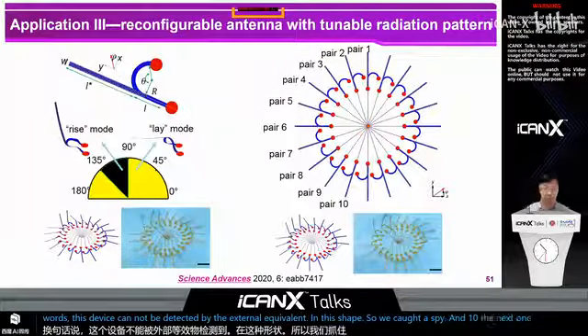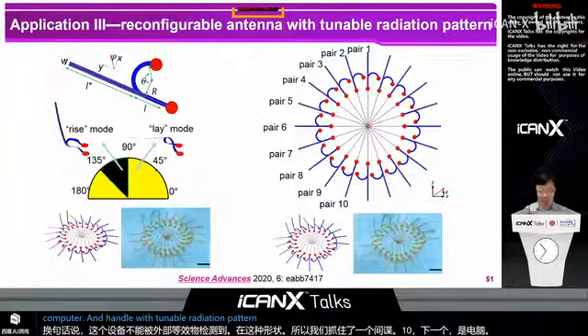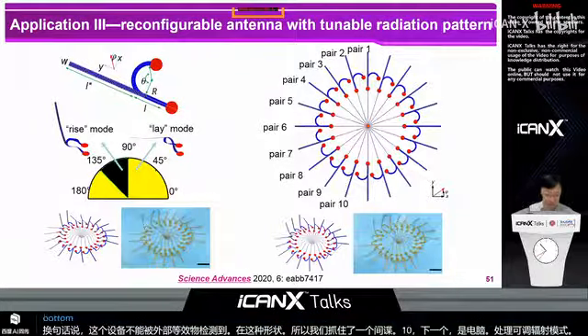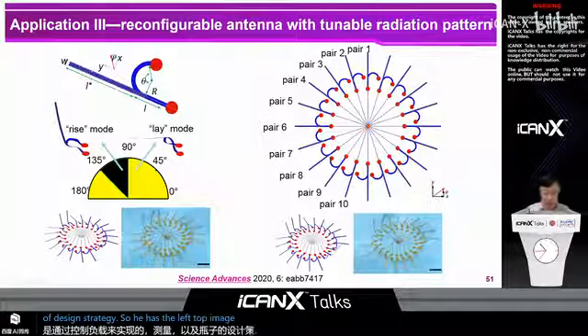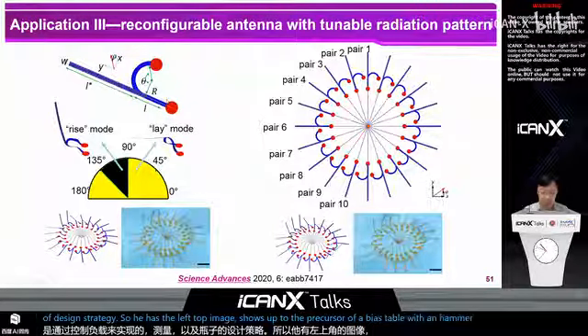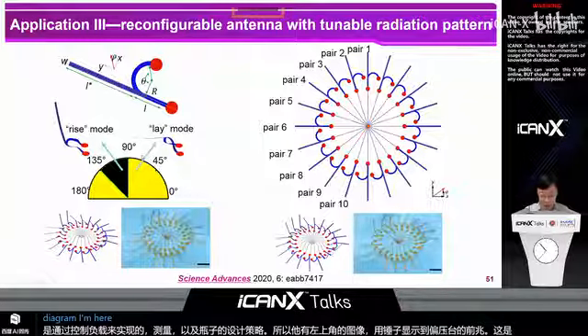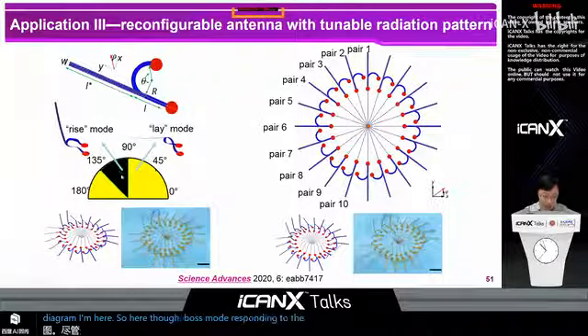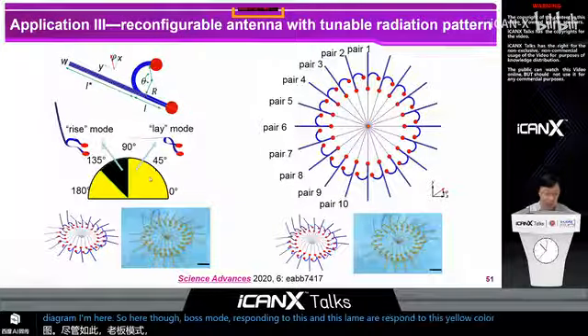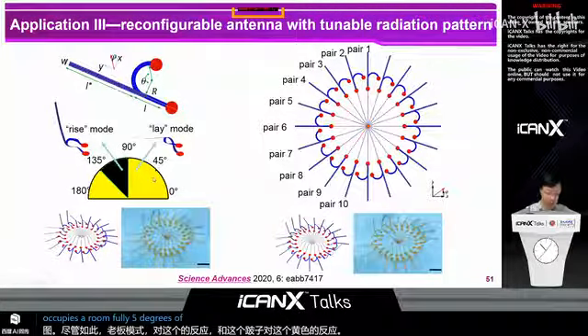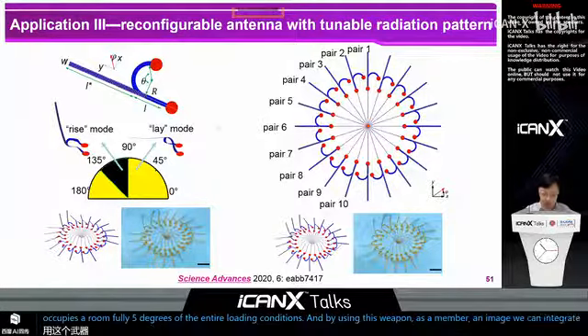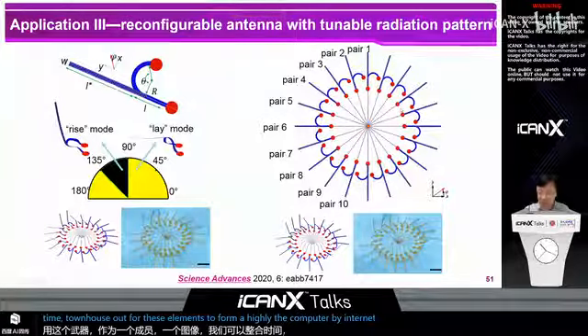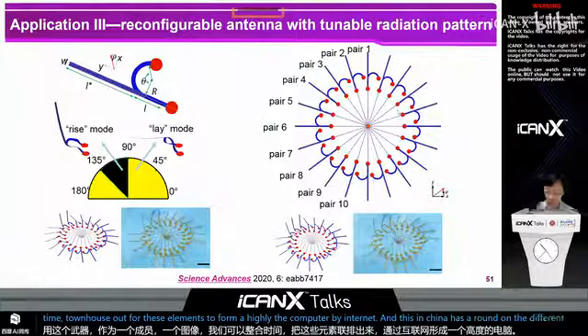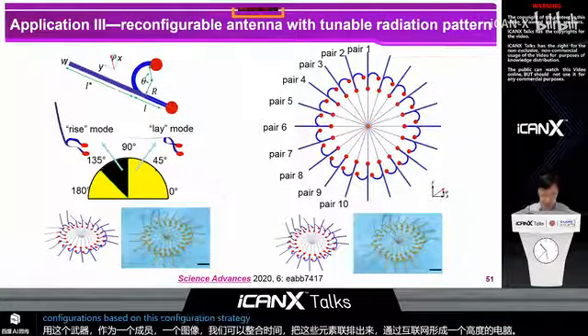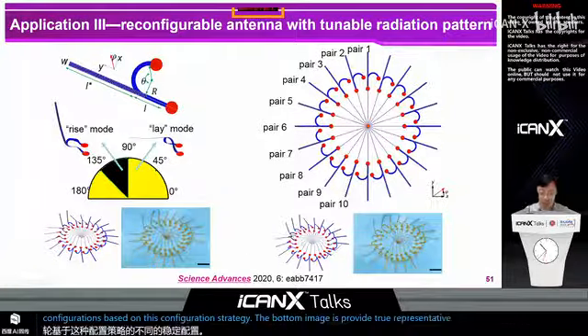The next one is a reconfigurable antenna with tunable radiation pattern. And this is realized with the loading path controlled method and the bottom-up design strategy. So here, the left top image shows the 2D precursor of a bistable wave antenna. And its phase diagram is shown here. So here, the rise mode corresponds to this black color, and this lay mode corresponds to this yellow color. And this rise mode occupies around 45 degrees of the entire loading conditions. And by using this wave antenna as a fundamental element, we can integrate 10 pairs of these elements to form a highly reconfigurable antenna. And this antenna has around 20 different stable configurations based on this reconfiguration strategy. And the bottom images provide 2 representative images of this stable configuration.